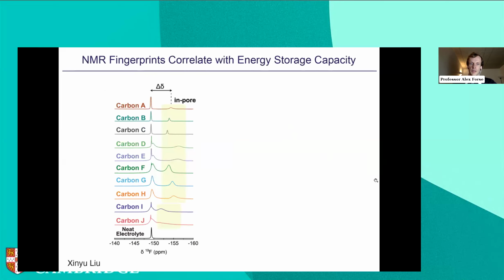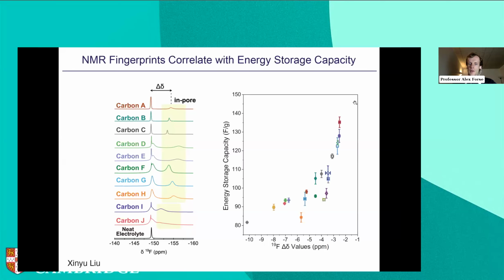So what Xinyu did is to measure these fingerprints for a really wide series of carbon materials. And we were really excited in this case to find that these fingerprints do correlate with how much energy we can store. So what we look at here is the difference in position of our 2 peaks in the fingerprint, represented by this delta delta. And what we find when we plot a graph of our delta delta value from these NMR fingerprints is that they correlate really well with how much energy you can store. And this is for 20 different materials from a whole wide range of different sources. And you can see broadly, when we've got a smaller difference between the positions of the peaks here, we get a higher energy storage capacity. So this is where we want to be, in the top right corner. And it sort of tells us where to go.